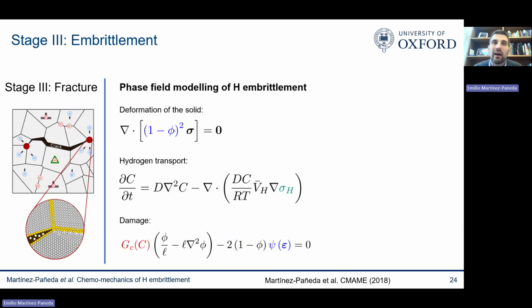But nothing had been done on hydrogen, so we proposed the first phase field model for hydrogen embrittlement. We proposed a series of models, but the simplest one you can think of is one where you solve for the deformation, diffusion, and damage process. I'm highlighting here some of the couplings, but of course the key coupling is this one: how does hydrogen reduce your fracture energy, your fracture toughness?